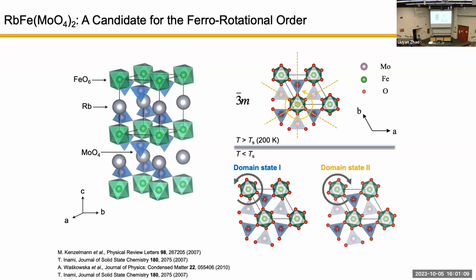There's a critical temperature below which the octahedral cage, shown in green here, rotates either clockwise uniformly or counterclockwise uniformly. Once this happens, we know the symmetry must reduce. However, people didn't know which symmetry it reduces down to. People tried diffraction techniques, but they gave three possibilities with equal likelihood among them.